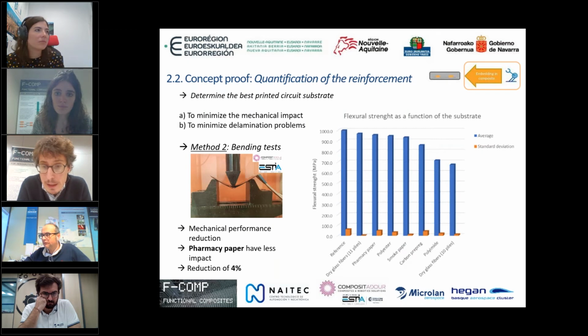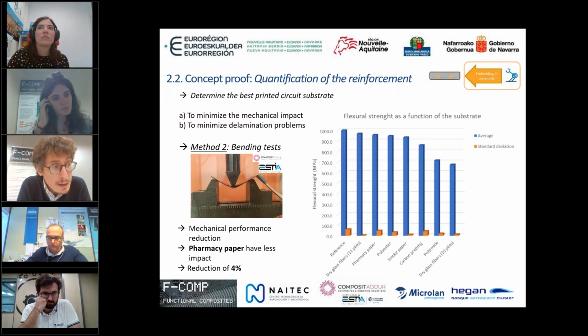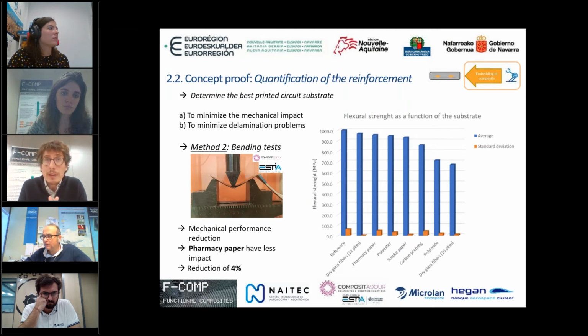But for example, the column that is more to the right is using dry glass fiber, and here we saw a very big reduction. Why? Because the resin was not properly transferred, because it was dry fiber put in between the pre-preg. Then the resin didn't go between the dry fiber, and we didn't manage to do the proper shear transfer